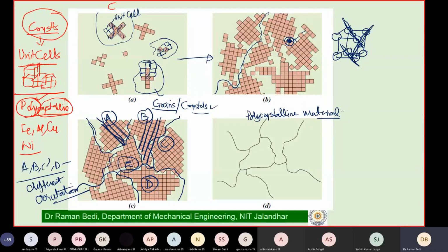So we said that the interatomic spacing is different amongst this direction and the other direction, and that is why single crystals will behave what we call anisotropically. Because in a single crystal all the unit cells are oriented in one particular way, all the properties will be different along this direction and different along some other direction, which has a different linear density. We introduced these concepts.